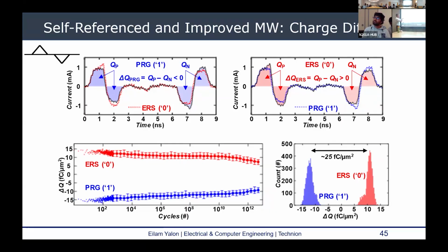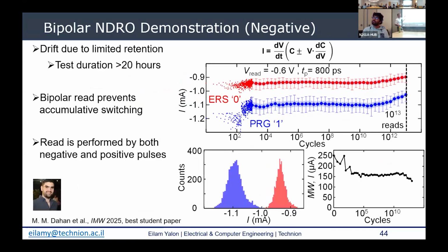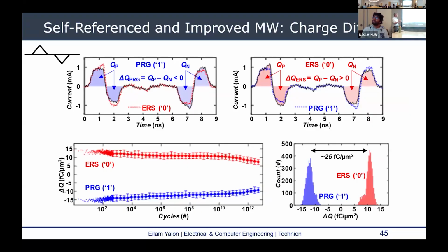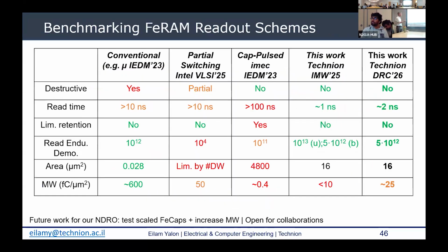So in terms of charge, we get a much clearer separation between the states, and it's self-referenced, unlike the current. For the current, we needed some reference, but for the charge, there is no reference needed. You directly get a positive charge in the erase state, negative charge in the program state, and it's non-destructive after the 10 to the 13 cycles. So we think that can be pretty useful. It's just benchmarking those non-destructive readout techniques.